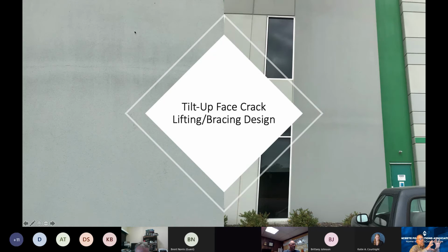And so the scheme that was used to lift these panels, the concrete wasn't rigid enough, or think of it as the panel wasn't rigid enough, and it literally folded or began to fold. It's in theory or in moment began to fold sufficiently that a crack developed on the outside. And so these cracks, again, were pretty easy to calculate. What we ended up doing here is we brought in a consulting engineer that actually did a real quick look at the design and looked at the concrete strengths, the breaks at the time of lift, and found out that the modulus of rupture was about 50% of what it should have been.